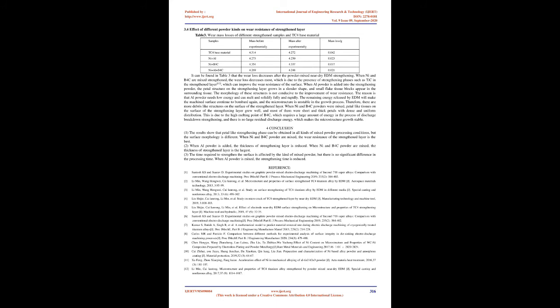Under the same processing conditions, the melting energy of Al powder is small and the melting rate is fast. In addition, due to the light weight of Al powder, it is easy to float in the solution and is not easy to be melted to the processing surface. In Figure 2, it can be clearly seen that with the addition of Al powder, the thickness of strengthening layer decreases. When Ni and B4C are mixed, the thickness of each position is the largest.